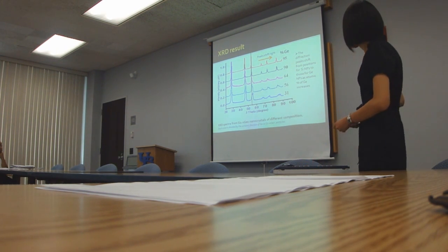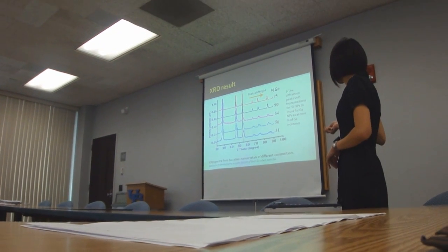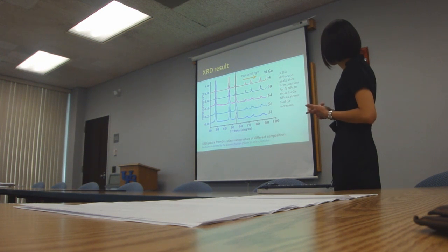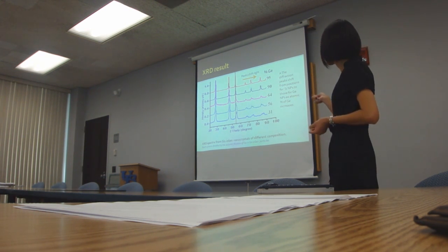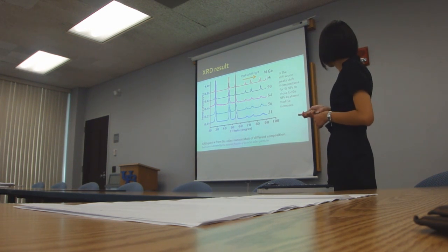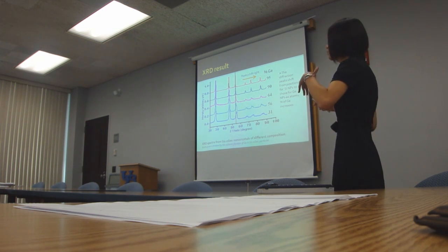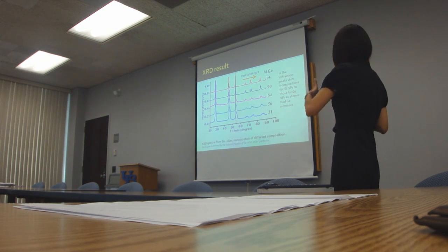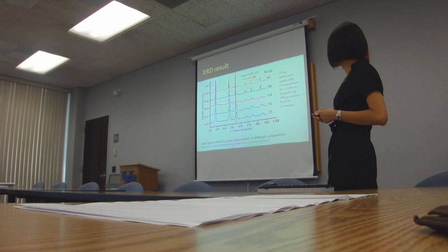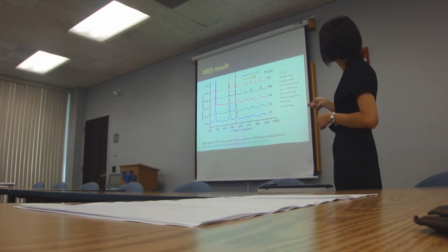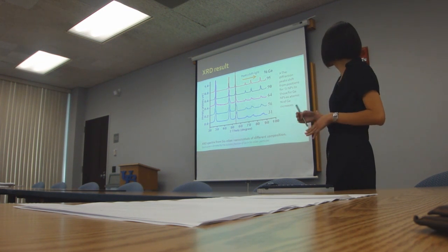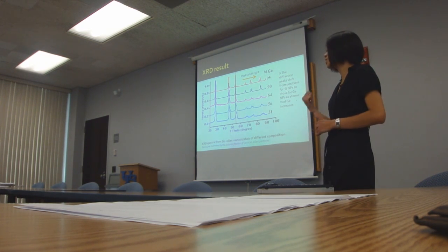Okay, so you can see here the atomic fraction of germanium increases from the bottom to the top. So if I have to draw a curve for germanium particles, which has a concentration like 100%, I will draw that curve on the top, and I will draw the curve for the silicon particles on the bottom. And we have the trend, the curve has a tendency of shifting to the right as the atomic fraction of Ge increases. So the curve will shift from this corner to this corner as the atomic fraction of Ge increases. So that's what I mean when I say that the peak shifts from the position for silicon particles to the position for germanium particles.